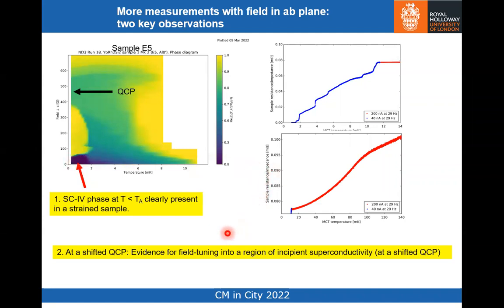But what's interesting, so that's one thing. The other thing is that you can see, yellow indicates normal state. So this is the re-entrance of the normal state. And then as we approach the quantum critical point, we see a reduction in the resistance that, and I had to use a thesaurus to find the right word, hopefully is incipient superconductivity at a shifted quantum critical point. In this particular set of measurements, the resistance is only dropping by about 20% from its normal state value, but it is dropping, and the color plot shows the systematics of how that's dropping. So there's something interesting happening in the vicinity of the quantum critical point. And if we measure it on a better quality sample, and maybe in a slightly different way, we could reveal something in that.